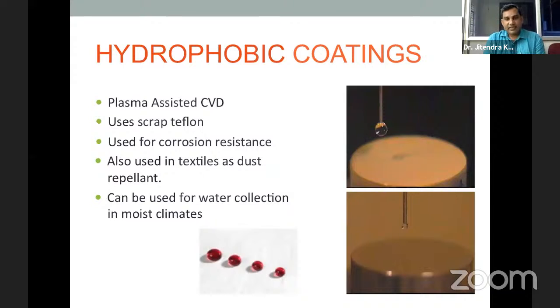Another type of coating is hydrophobic coatings, which is generated by plasma assisted chemical vapor deposition. So you can see on the coated surfaces the drops of water are very spherical in nature. That type of coating is very important for several aspects, like self-cleaning glass in the real estate industry, self-cleaning solar panels. These types of coating are very widely used in these areas. You can easily see these droplets roll out over the surface. So that is a hydrophobic coating.